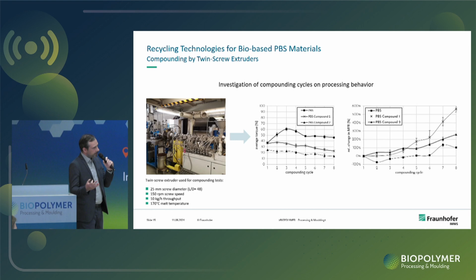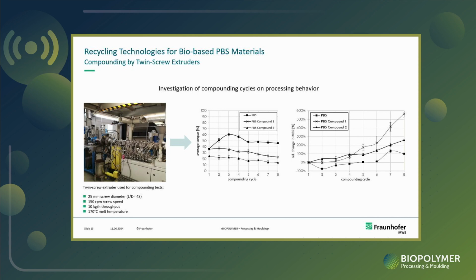Good, and then the next step, once you have sorted out, you have collected, you have milled your material, you can start to do the reprocessing, the recompounding of the material. And here we worked in our own lab with a 25 millimeter twin screw extruder. And we did different recycling processing steps, so reprocessing steps of the material, up to 8 cycles. And in the first diagram, you can see the development of the torque of the twin screw extruder.